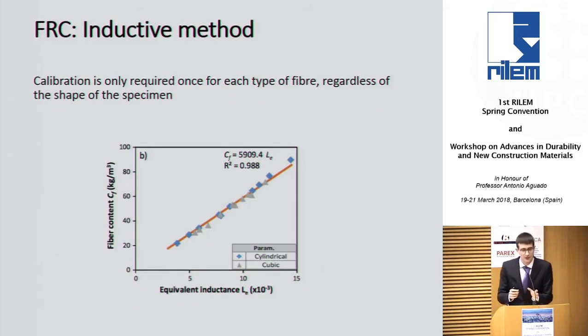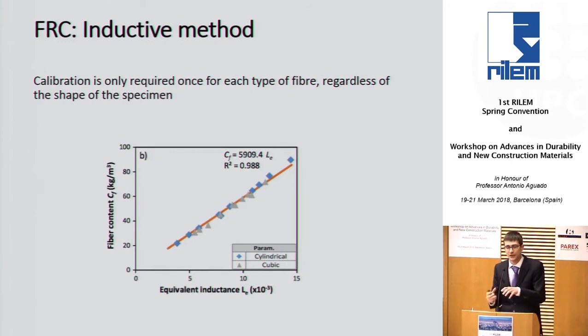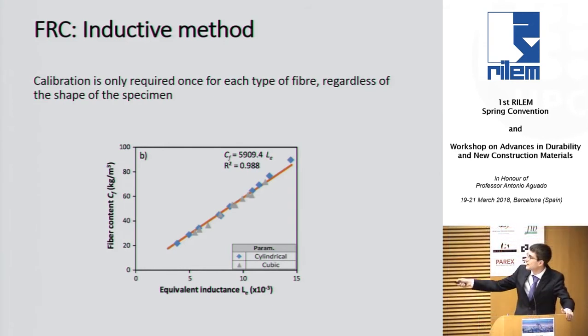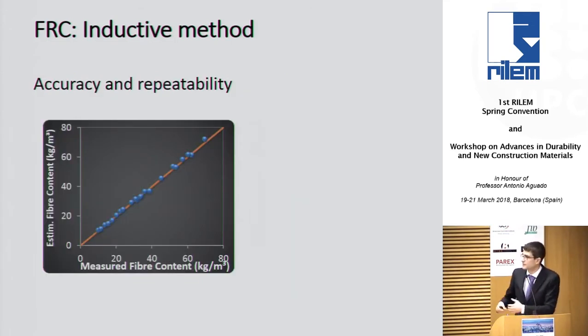So the equipment works very well. You place a specimen, in this case, it has to be metallic fibers, and you place it inside the equipment, you can measure in three directions, and that's enough. You have the results, you have fiber content and fiber orientation. So this is just a graph to show the equivalence between fiber content and the result from the test, the inductance measurement from the test, for different types of specimens. You see a very straight line. So there is a calibration, a very good relation between the measurement from the test and the fiber content, right? We have tested and assessed this accuracy in different ways, different temperatures, and the results are always good like that.